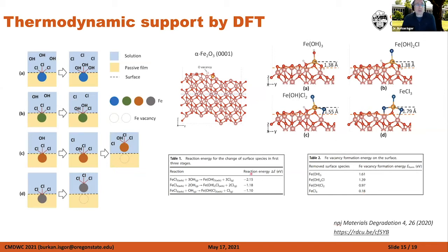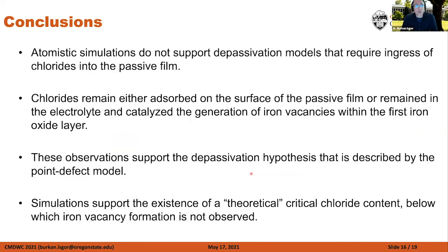So DFT simulations all confirm thermodynamically in a way that what I showed you in molecular dynamics simulations were also correct. Well, I shouldn't say correct, but they supported each other basically. Now the conclusions: atomistic simulations that we have carried out did not support the depassivation models that require ingress of chlorides into the passive film. Our simulations showed that chlorides remain either adsorbed on the surface of the passive film, or remain in the electrolyte, and catalyze the generation of iron vacancies in the oxide film.